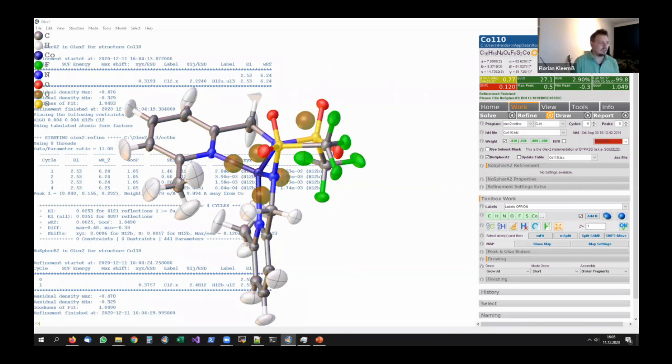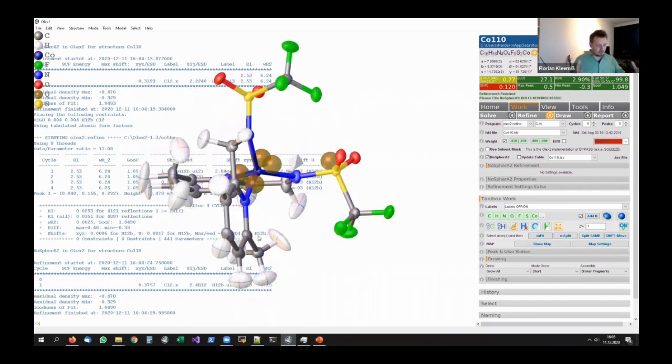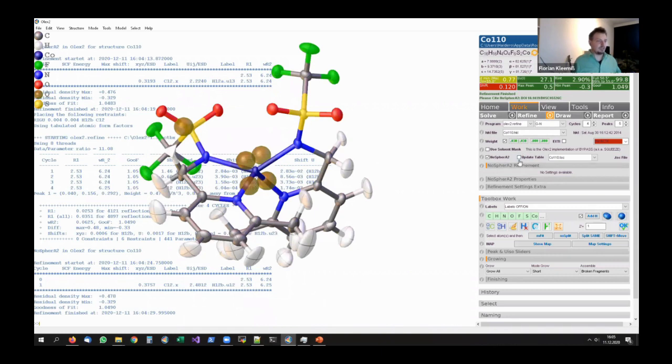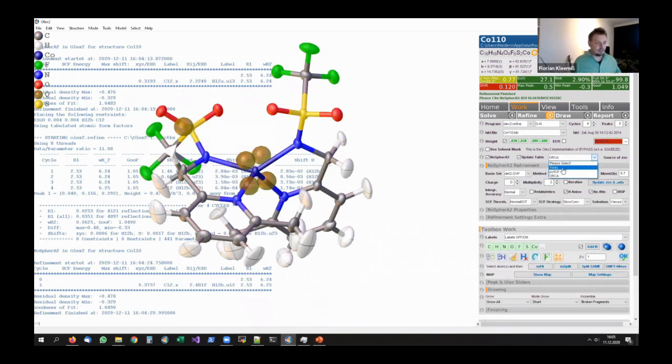In Tonto, there was the possibility to also generate charges which would correspond to the crystal symmetry and model the crystal environment of the calculation, which we have not successfully implemented so far for ORCA or PySCF. But if you go to Tonto, there is the cluster radius. So in this case, you can input the radius until you want to grow the cluster and calculate the wave function using Tonto. However, in Tonto, you have a very limited choice of methods, and Tonto is relatively slow. So in the future, we want to implement this also for the other techniques, ORCA, PySCF, Gaussian.